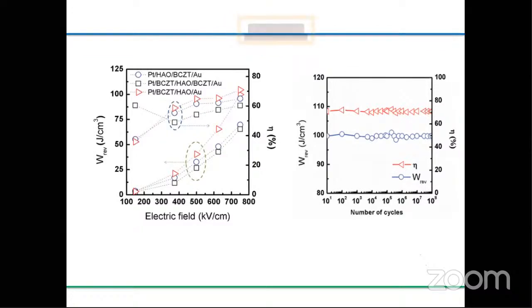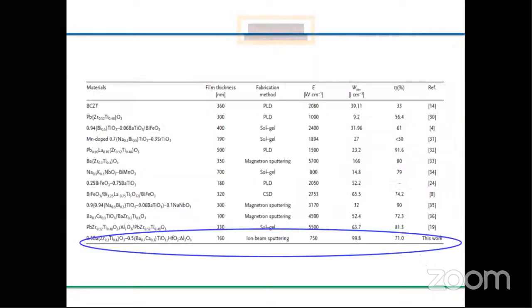When you want to apply this for real-time applications, we need to check how many times we can charge and how many times we can discharge. When doing this repeatedly, some capacitors will not work, so we need to test for practical implementation. We applied up to 10^8 cycles and measured the recoverable energy and efficiency. They are almost constant, so we can use this for practical applications. We compared our work with different materials. Here we are using 160 nanometer thickness, and the method is ion beam sputtering. We observed 71% efficiency at an electric field of 750. Still we can improve by modifying some conditions, which is what we are doing right now.